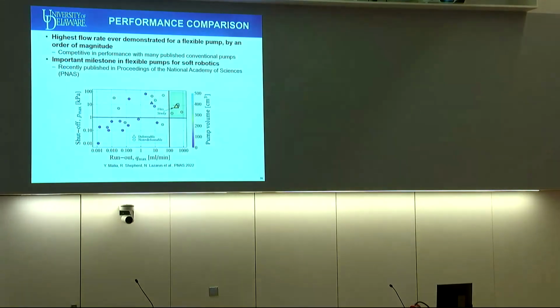And so using this, we're able to demonstrate the highest flow rate for a flexible pump by an order of magnitude. And so able to get performance much more similar to what we were able to do with conventional electromagnetic pumps, conventional rigid pumping technologies. So able to generate significant levels of pressure, able to generate significant levels of flow by relying on techniques that are well established in traditional pump design.